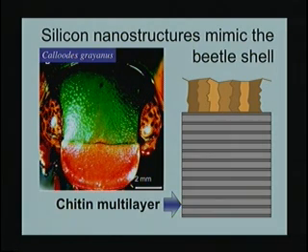And so it builds a more robust form of color that's akin to how rainbows have their color and thin soap bubbles get their color. They have a structure. A soap bubble has a very thin film, and the iridescence in that soap bubble that you see comes from interference of light in that film. The film itself is clear, but if it's thin, on the order of a few wavelengths of light, then it imparts a color to it. And that's what the beetle does.